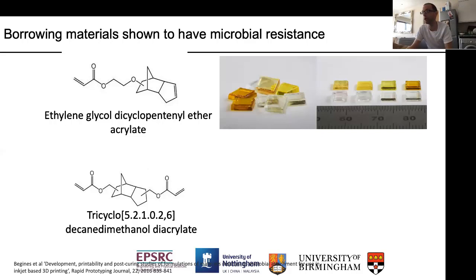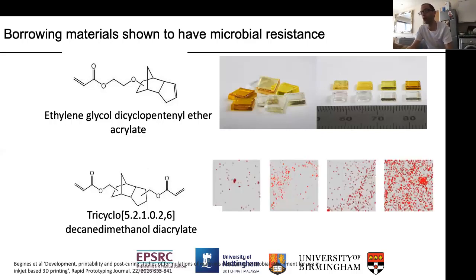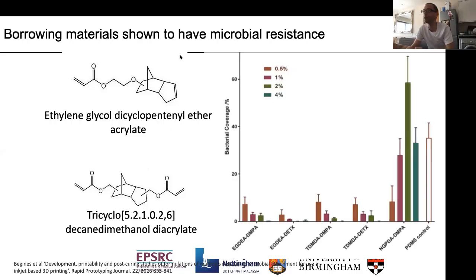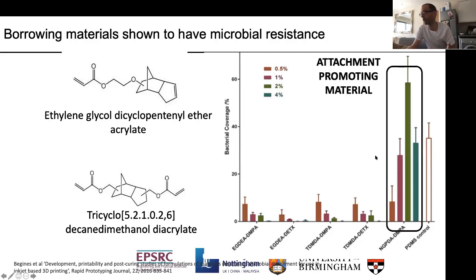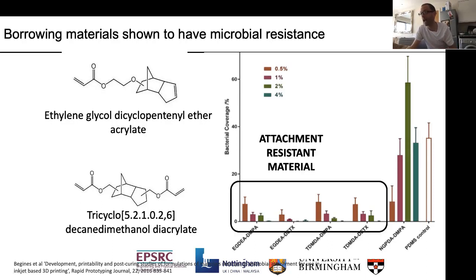And so we then scaled that up, printed samples, put bugs on them, and basically saw whether the bugs liked to stick to them or whether they didn't like to stick to them. And we were able to see that compared to commonly used materials, so PDMS, polysiloxane silicone, and materials that we knew would promote attachment, our formulations showed a really nice resistance to attachment. And essentially, these four formulations are variants in the amount of photoinitiators we had in. And we saw that the better curing you got, the better cell-instructive resistance to bacterial attachment that you got. So we were really happy.